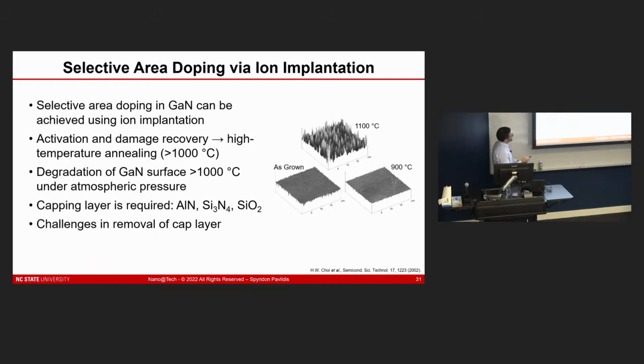So one of the things that people have done is to look at the use of different capping layers, effectively materials that you can deposit on top of the semiconductor before you do the anneal to hold the material together. But the main challenge that has come as a result of that is that at these high temperatures, the capping layer and the GaN actually start to interact, and it becomes very difficult to remove that capping layer and leave behind a clean surface to which you can make high quality contacts.